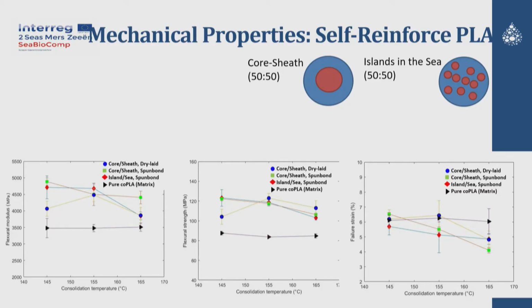The first material that we tested is self-reinforced PLA. We tested two different kinds of filament with two different cross-sections. The first one is core and sheath, which you can see on the top left figure. The second one is islands in the sea, where very small high-melt PLA is embedded in the low-melt PLA. As a second factor, we compared two different types of non-woven technology, dry-laid and spunbond. So we compared two cross-sections and two different non-woven technologies.